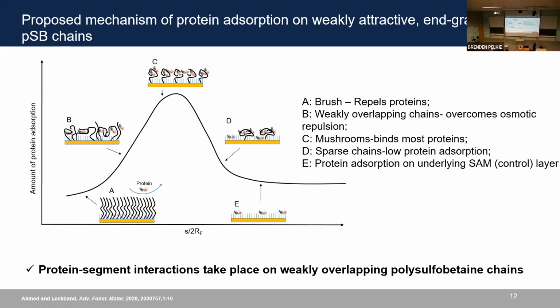When there is a highly dense brush grafted on the substrate, the insertion penalty for the protein is too high. So therefore we see low fouling or low protein adsorption. But as the distance between two neighboring chains increases, that means the grafting density decreases. Now the protein can overcome this osmotic repulsion by interacting with the surrounding polymer chains, which is attractive interactions.